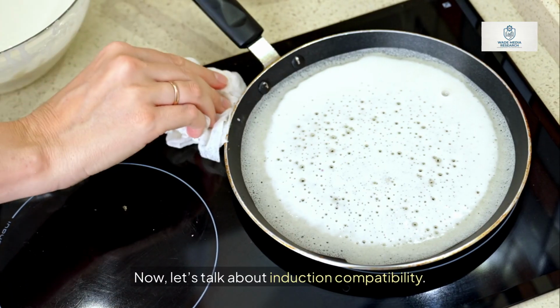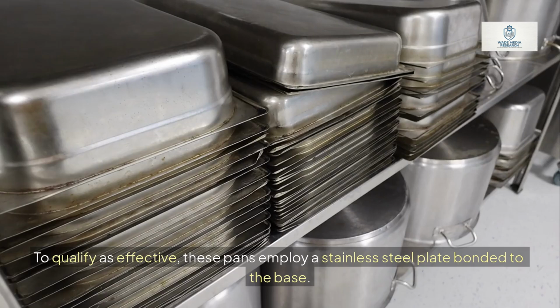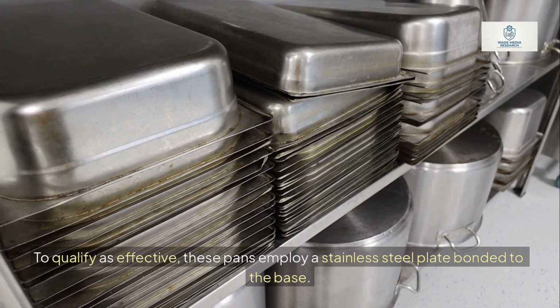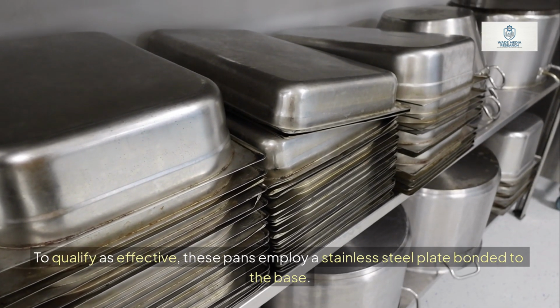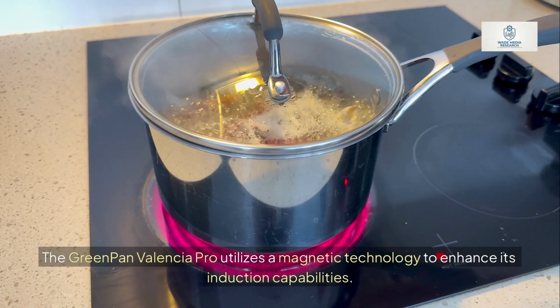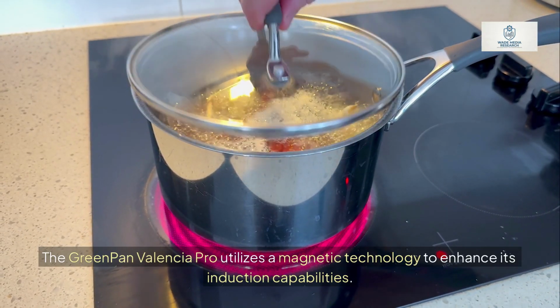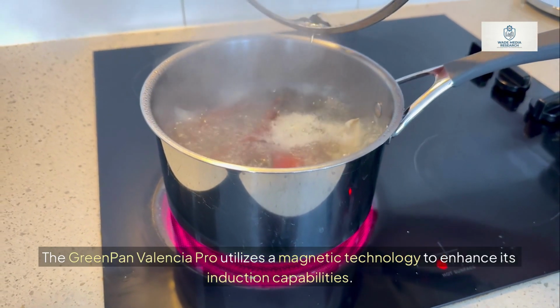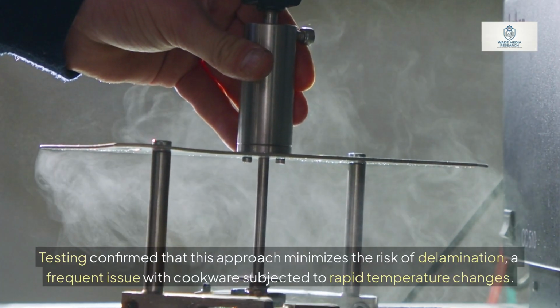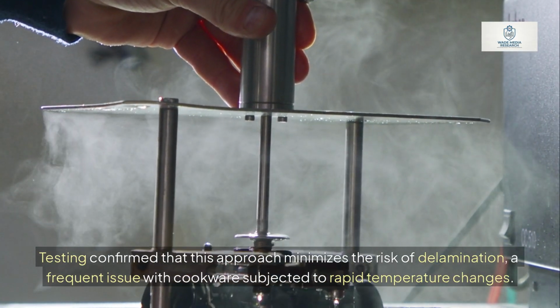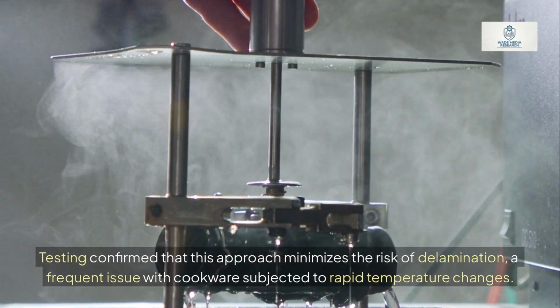Now, let's talk about induction compatibility. To qualify as effective, these pans employ a stainless steel plate bonded to the base. The Green Pan Valencia Pro utilizes a magnetic technology to enhance its induction capabilities. Testing confirmed that this approach minimizes the risk of delamination, a frequent issue with cookware subjected to rapid temperature changes.